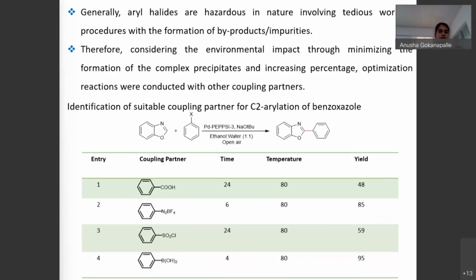When we changed the coupling partner to benzoic acid, we got 48% yield because breaking of benzoic acid required high temperature, and also due to some reasons we got less yields. And next we tried with diazonium tetrafluoroborate and sulfonyl chloride and boronic acid. Among these, sulfonyl chloride also gave less yields, but in case of boronic acid we got 95% yield.